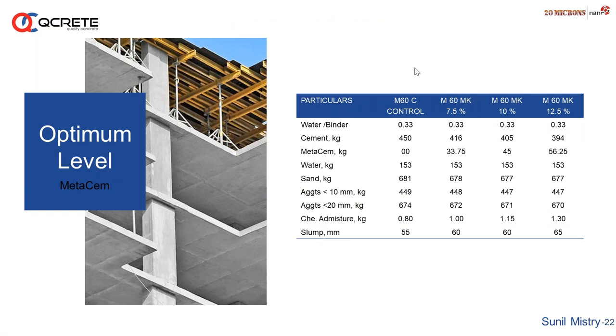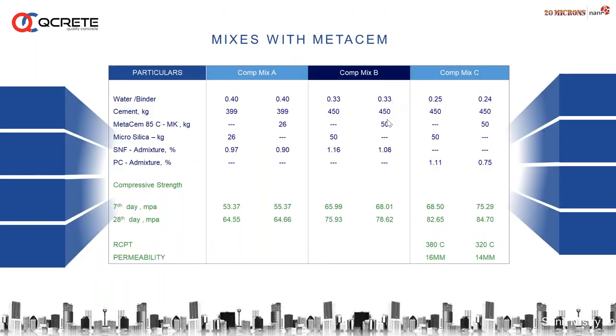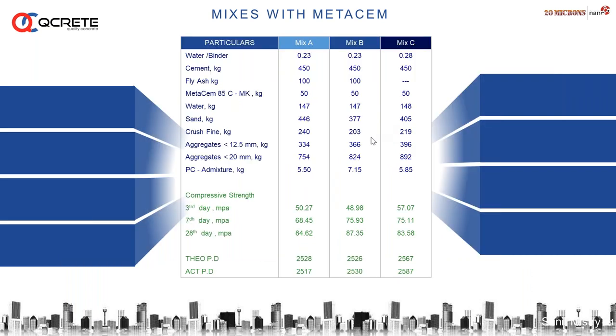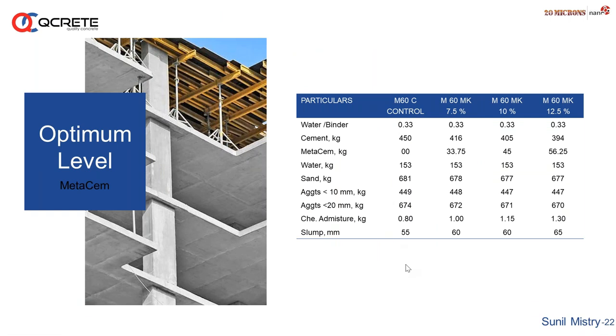And this is the question that always comes, what is the ideal dose? Because somewhere you can see we added 50, somewhere we added only 26 kg. Somewhere it is like 5%, 7%, 10%, and what actually. So we conducted one trial in consistency, not adding any other things, keeping the water cement ratio constant for M60 grade of concrete.